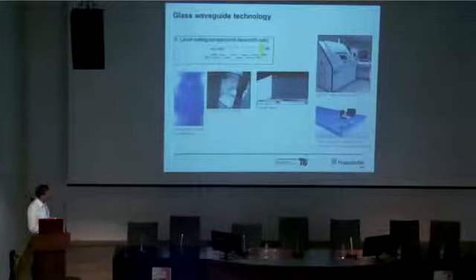So there we have a laser cutting system in-house, and this works in such a way that we give an initial crack to the edge of the glass, and then we move this crack through the glass along a line, and this will be done by thermal stressing the glass. So we have a CO2 laser that locally heats up the glass, and just behind is water cooling that cools the glass immediately. So this crack really moves along a line, and we're getting a very nice optical end face, and we can use this for optical coupling.